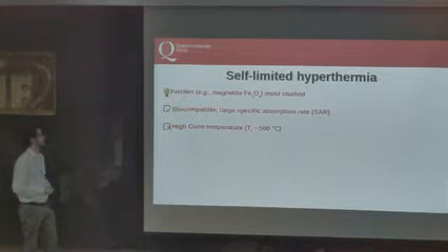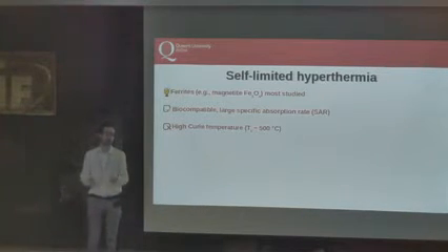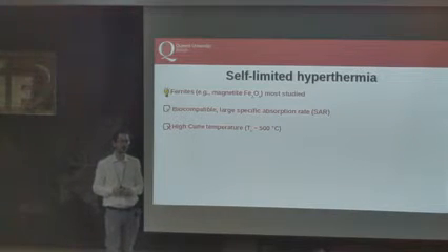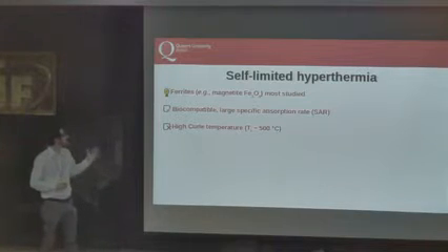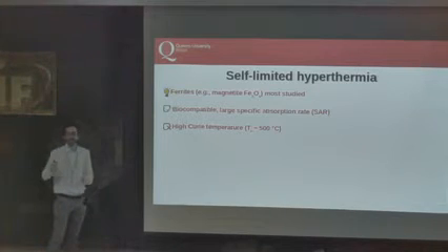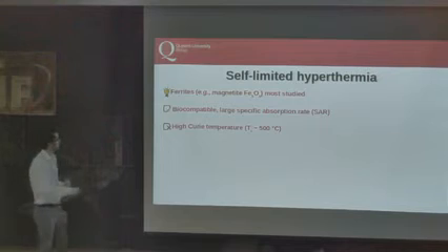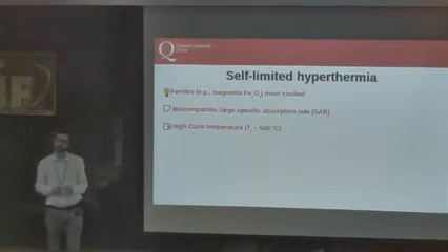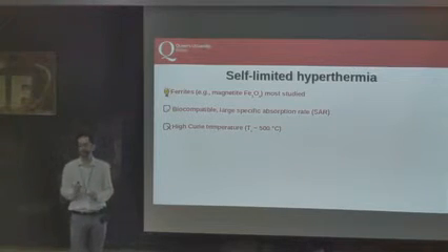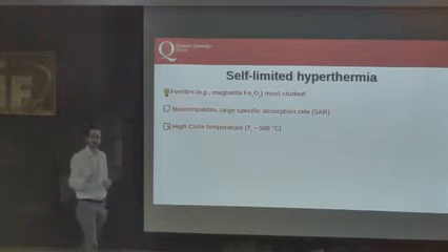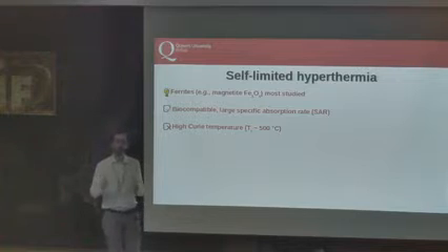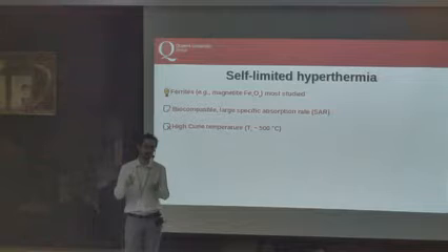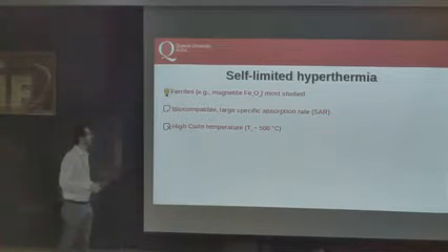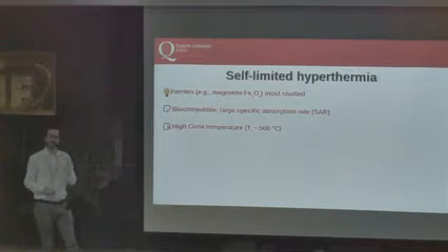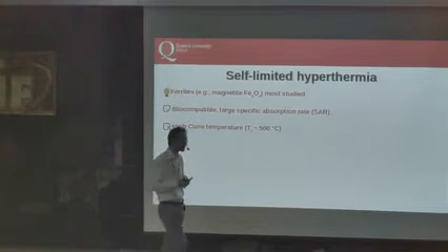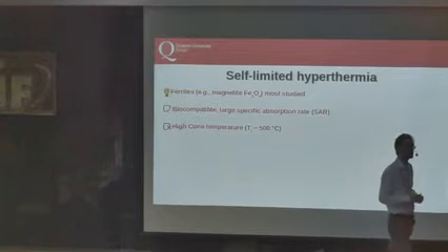This is very good, it's biocompatible. Very large values of the specific absorption rate, so the heating power, have been reported. It's not toxic. There is just one issue. If you just leave your magnetic field on, these particles can heat up considerably. In fact, the only intrinsic mechanism to stop these magnetic nanoparticles from heating up is the Curie temperature. At a certain point, the magnetic nanoparticles are no longer ferromagnetic. It's the Curie transition, and they are not going to heat anymore. So they're very good at heating, but it's difficult to control this heat. Is there any other candidate that one can possibly use that has better controllability?